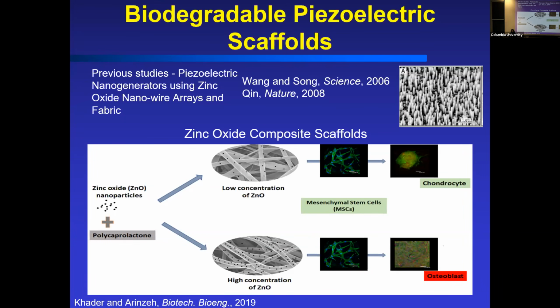And so eventually we would ideally like this material to degrade, right? And you get the formation of the healthy cartilage tissue. So we've been looking at biodegradable versions of this. And as a first go round, we looked at incorporating or making composites that contain zinc oxide. Zinc oxide is well known to also have piezoelectric properties. It's been shown in other fields as electric generators in various forms, but we can incorporate this into our fibers by, again, incorporating those nanoparticles into the fiber. And again, low concentrations of the zinc oxide into those fibers.